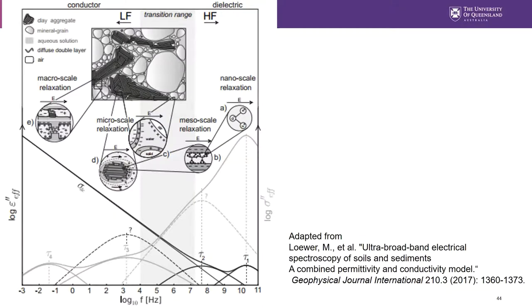it's not as simple as we would like, because depending on the frequency range, you will have different polarization processes. When I say polarization, I talk about the way materials get polarized by an electrical field. If we just have a look at this gray curve, if we start at the very, very high frequency, what is very important is that the processes depend on different scales, so on different frequencies. At the very, very high frequency, we have what we call the nanoscale relaxation, and here we interact with the electromagnetic properties of the molecules of water within the soil. This is typically microwave.